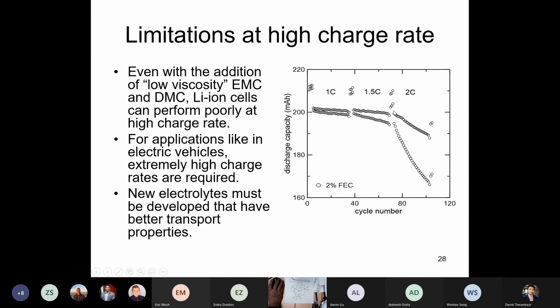And this is because the charge rate has been made so high that the overvoltage developed in the electrolyte is so large that the graphite electrode is pushed below 0 volts and you get lithium plating on its surface. So the transport properties of this electrolyte need to be improved to accommodate a 2C charge. Any questions about that?